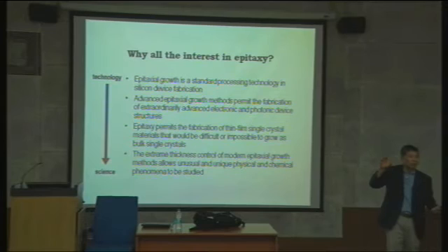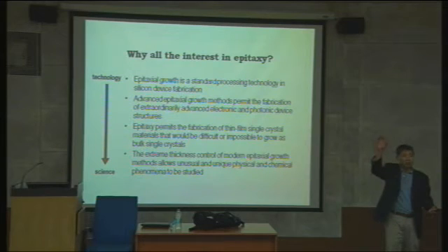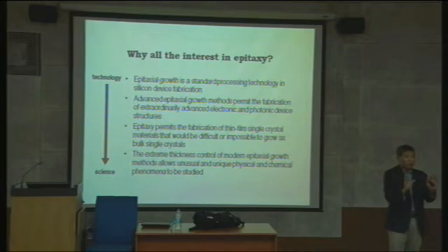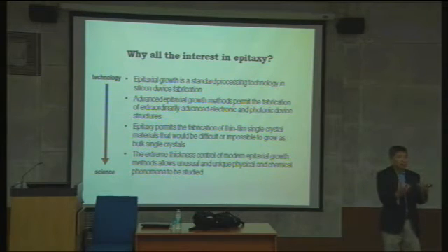It's not the same as the substrate perovskite material. If you grow this material as a bulk single crystal, melt and cool down, it forms the pyrochlore phase, which is an undesirable phase. But when you grow exactly the same material on top of the perovskite substrate, the substrate lattice forces it to form the perovskite structure, because the atomic bonding underneath forces them to do that. That is what we call substrate-induced metastable phase formation, which is one of the beautiful pieces of science and discovery of new materials using heteroepitaxy to stabilize metastable phases.